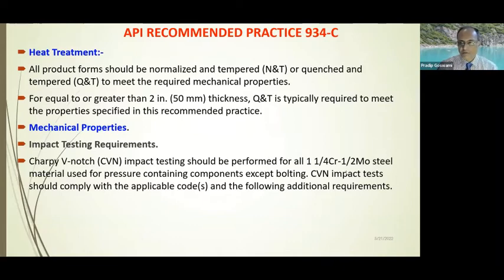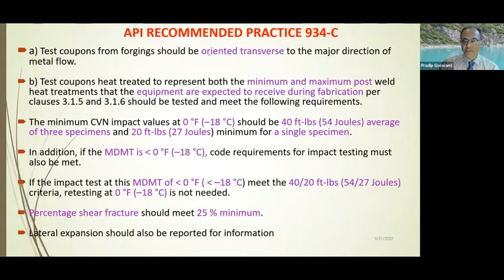Charpy impact test should be performed for these steels, and Charpy impact should comply with the applicable code and the additional requirements as mandated by the project. And Charpy impact test for forging shall be typically transverse to the direction of the metal flow, and you know it very well, because when you do the forging, there is always a grain elongation or grain orientation depending on which direction the deformation is done.